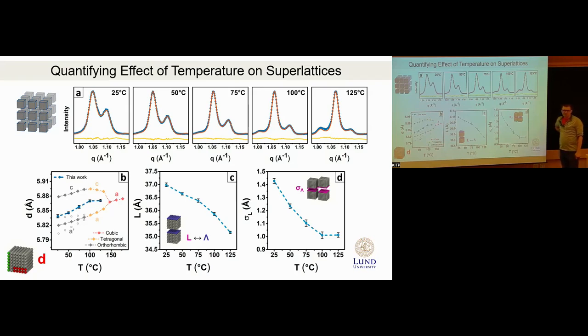Well, you could get that from the 2D data, because the more orientational mismatch you have, the broader your arcs are going to be. So if you go back to the 2D data, you should see that if they are coalescing, the arcs will get narrower and narrower. That should be pretty easy to check. I would expect the fact that you see this at all indicates that they're probably pretty well aligned to begin with, and you're just gradually aligning a little bit more. Okay, that's a good suggestion.